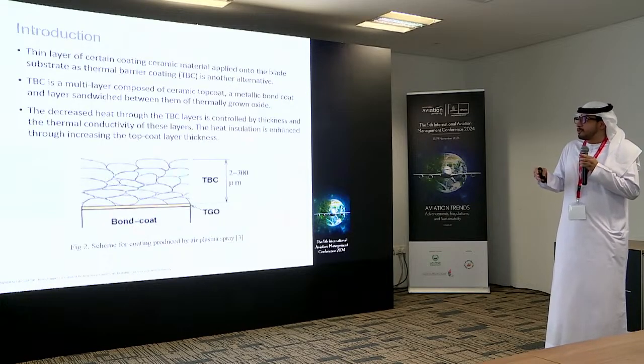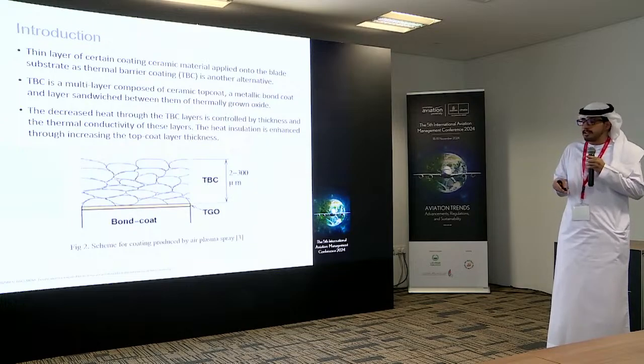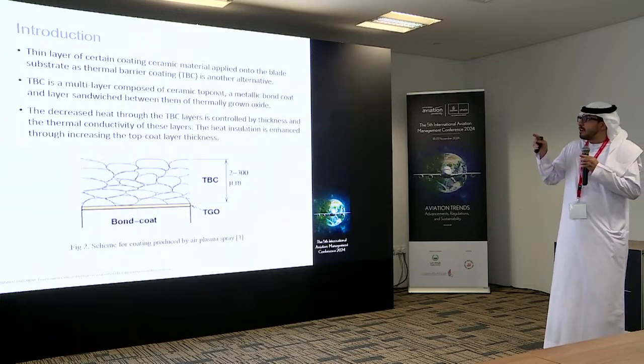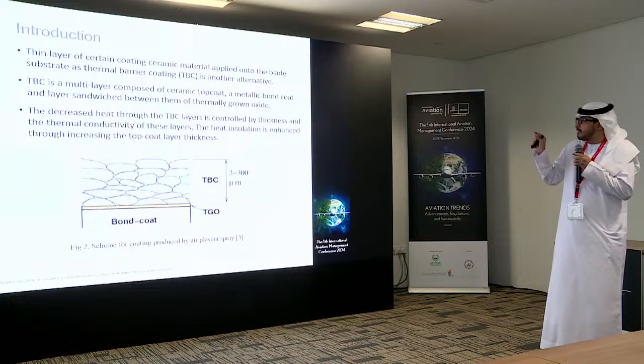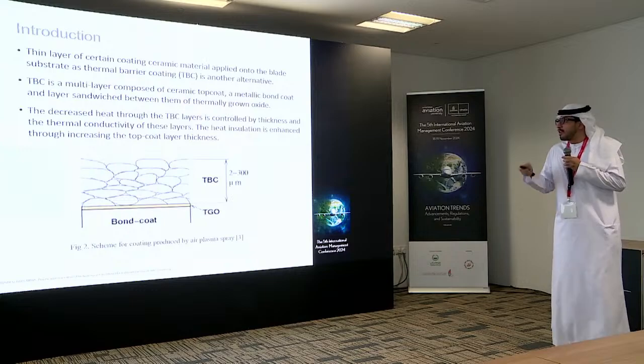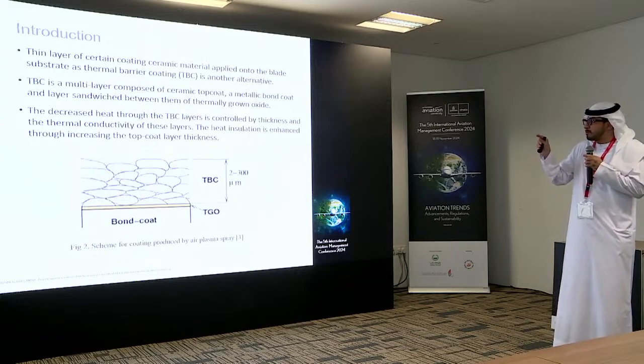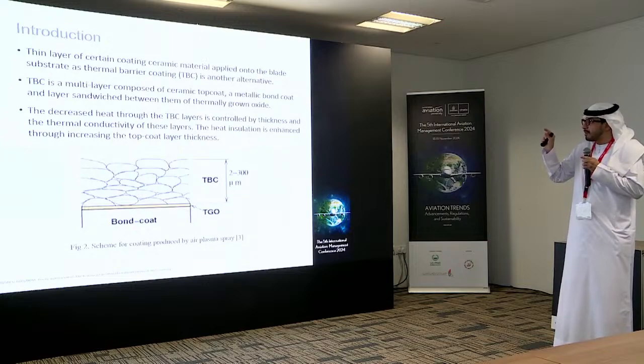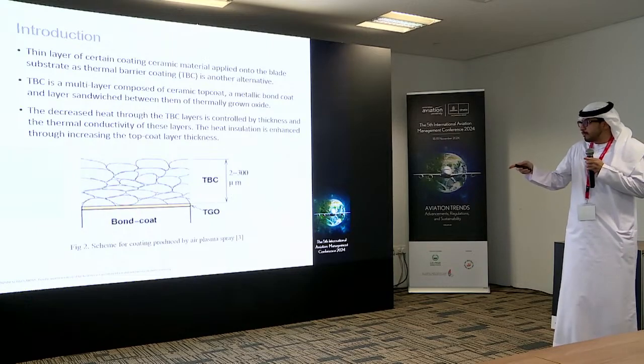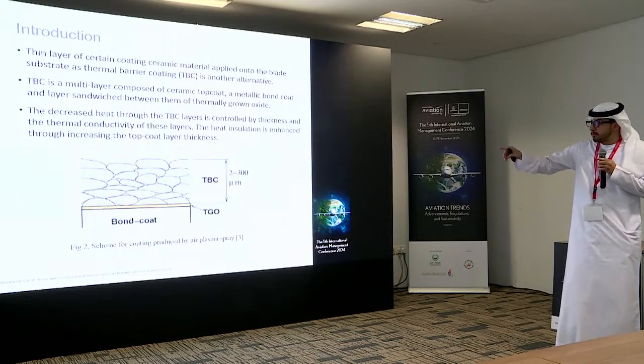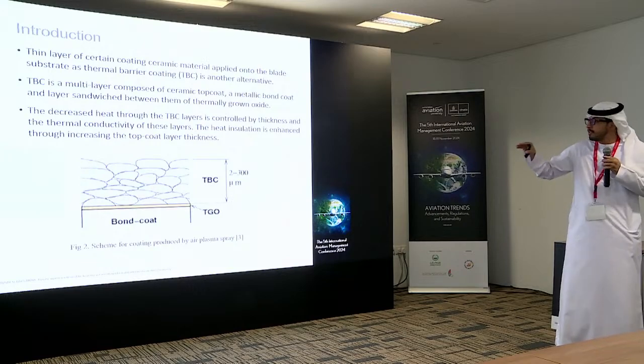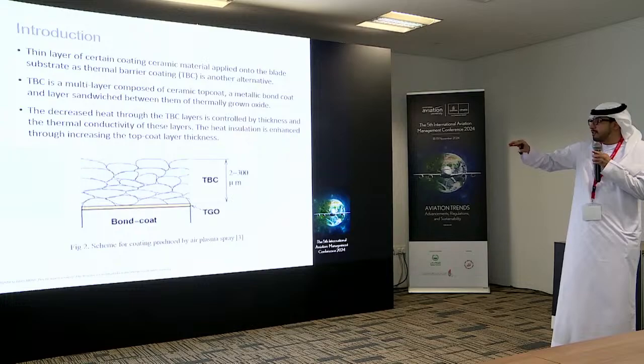However, a new perspective has been suggested recently by ceramic researchers. Thin layers of a coating ceramic material are applied onto the blade surface as a thermal barrier coating, or TBC, which is another alternative. Thermal barrier coating is a multi-layer composed of a ceramic top coat, a metallic bond coat, and a layer between them called the thermally grown oxide. In figure 2, you will see the 3 layers: the bond coat, which comes directly after the surface of the superalloy, the thermally grown oxide, and then the thermal barrier coating, which goes from 2 micrometers up to 300 micrometers.